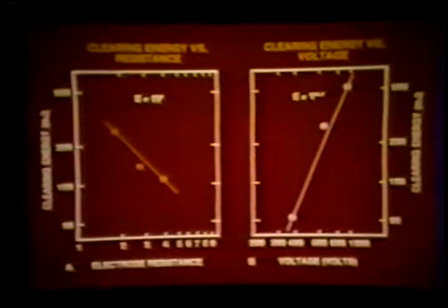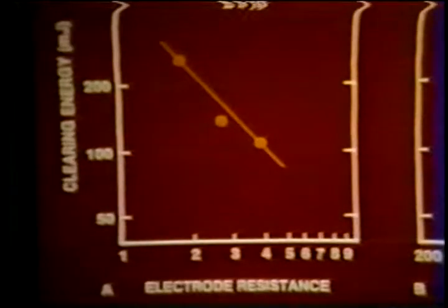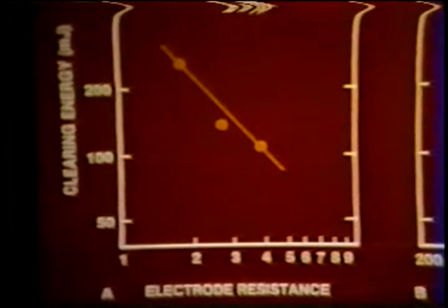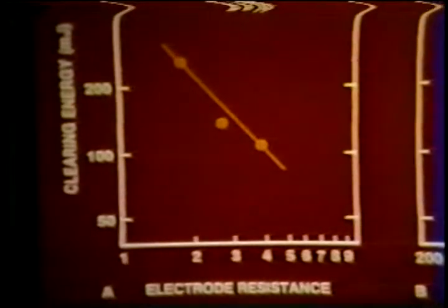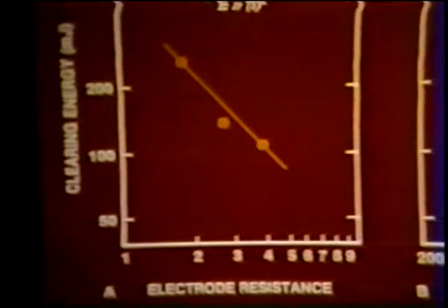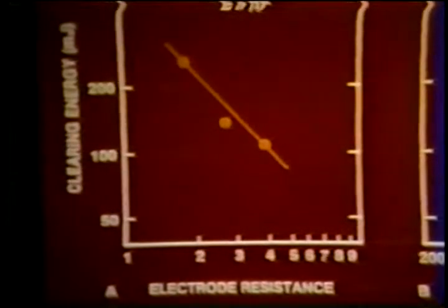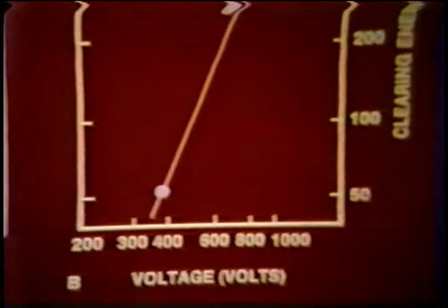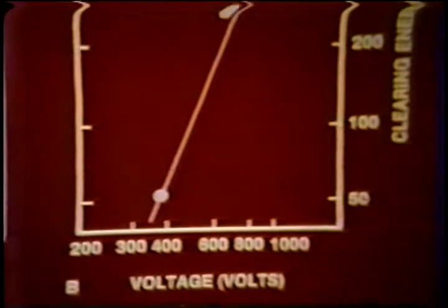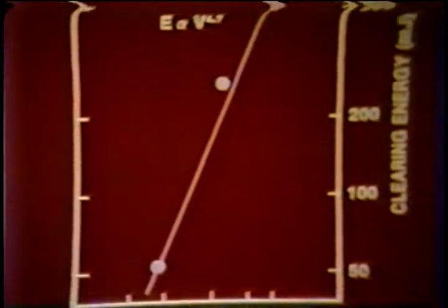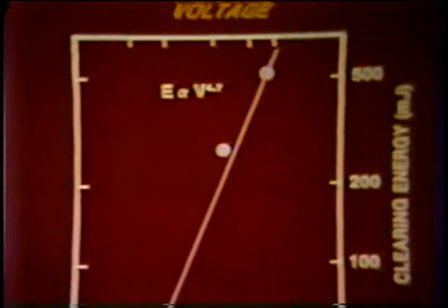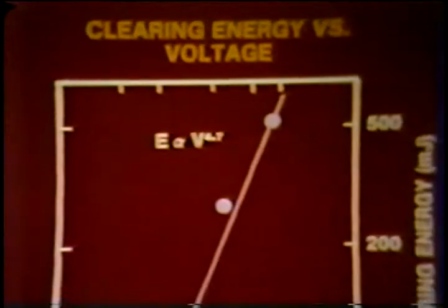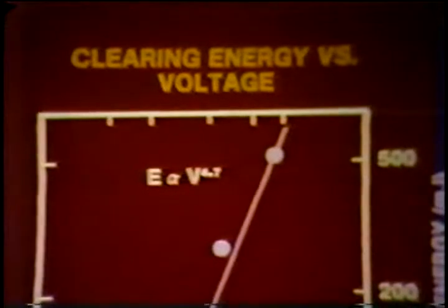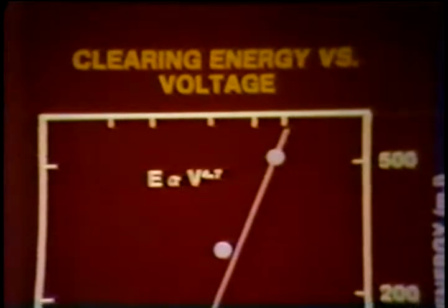In the case of the electrode resistance, we see that as the electrode resistance is increased, the clearing energy quickly is reduced. This energy is inversely proportional to the square of the resistance. In the case of the applied voltage, we see that as the voltage is increased, the clearing energy rapidly increases. According to the relationship, the clearing energy is proportional to the voltage to the 4.7 power.